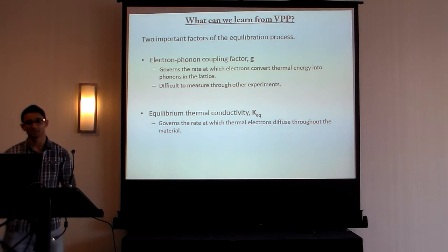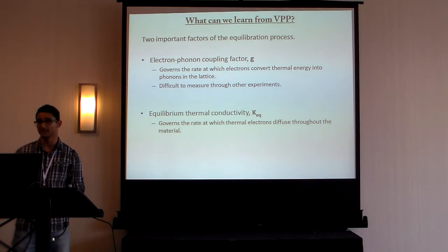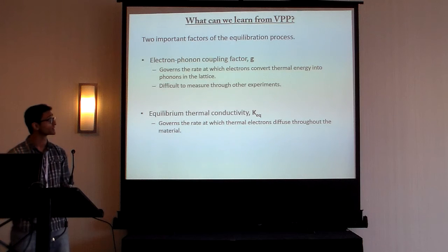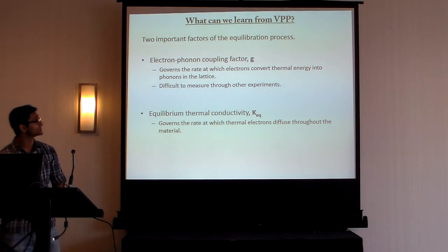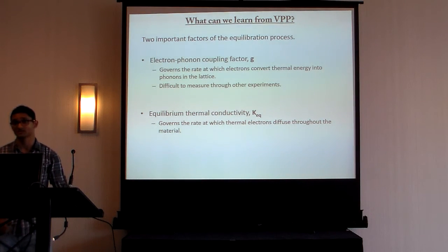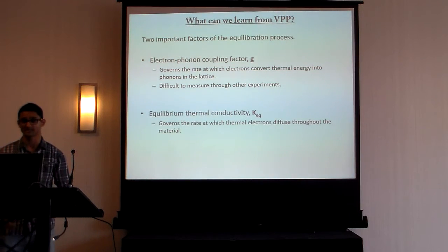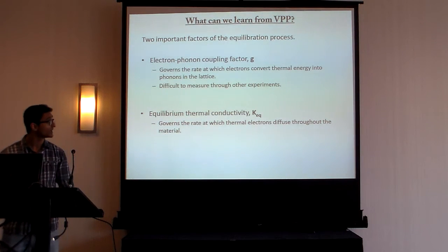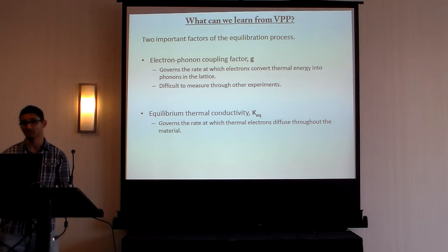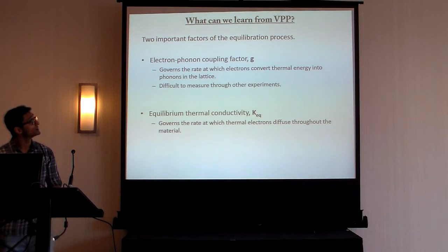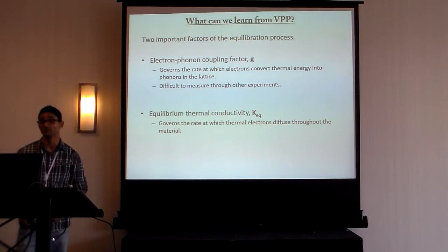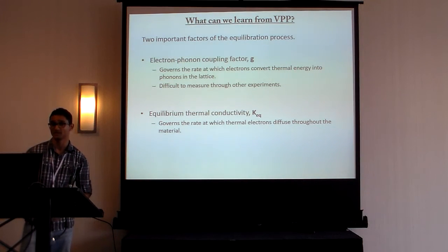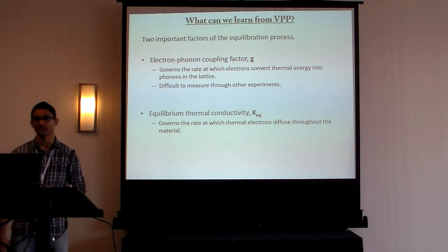So what we can learn from this experiment are two key factors of the equilibration process. The first is the electron-phonon coupling factor, G, which governs the rate at which electrons convert their thermal energy into phonons in the lattice. And this is somewhat difficult to measure by other experiments, so pump-probe spectroscopy is very useful in that sense. Another parameter we can get out of our experiment is the equilibrium thermal conductivity, which governs the rate at which thermal electrons diffuse throughout a material.